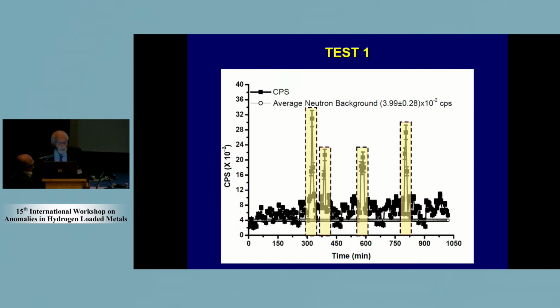But you see that we have a direct comparison between background, which is about 4 CPS, but also there is the power of 10, 2 minus 2, of course. You can see the scale of the neutron emission. And you see that we have on the left a first very clear peak or burst, which is more than 8 times the background. Then the other 3 are a little smaller. Okay, this is the most important thing I believe to observe.